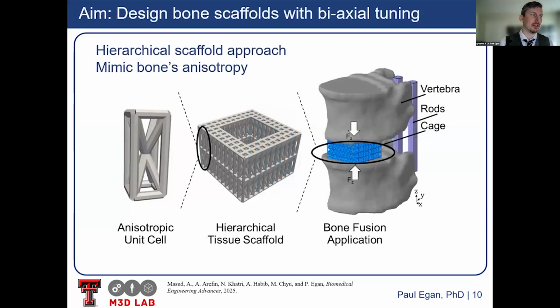And our approach for this is going to be hierarchical. So we have the anisotropic unit cell, which we're going to longitudinally stretch or squash. That's going to change the direction and the magnitude of the elastic modulus. Then we're going to arrange those unit cells into a hierarchical scaffold. That scaffold has a big central pore that's going to allow nutrients to get through and also vascularization, or blood vessels, to form. And then we can implement it and test it in the bone fusion case study.